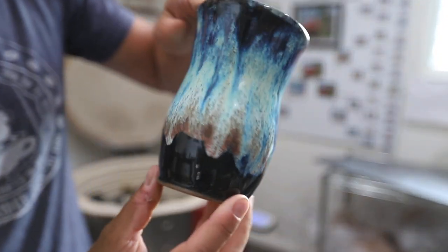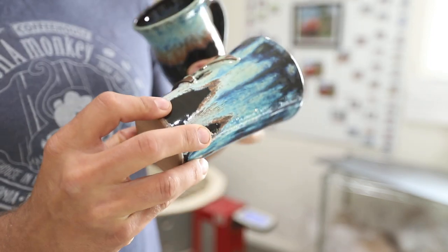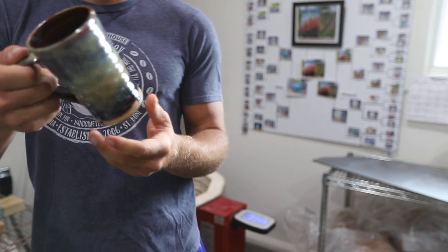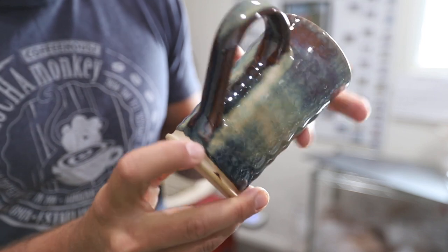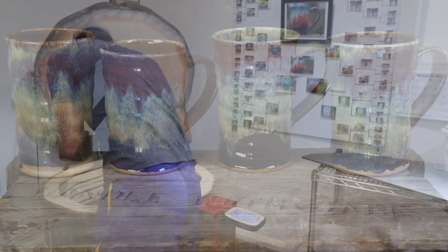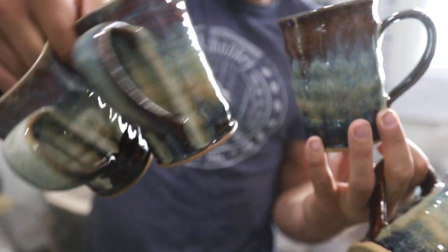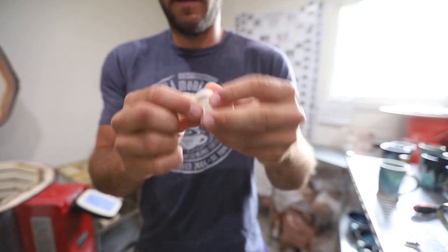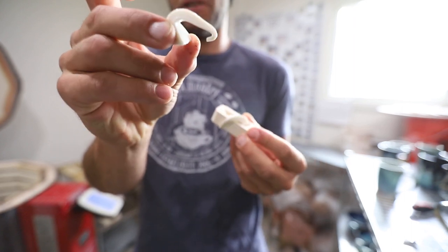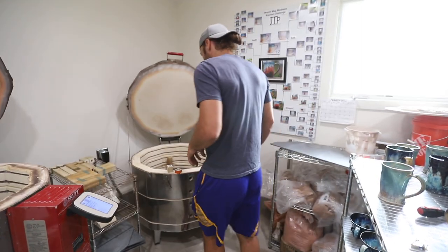There's a Northern Lights mug that dripped all the way to the bottom and off. Not sure why it's dripping over the top of the Minnesota. The glaze I haven't done in forever — Canyon Skies. If you guys have been following this channel for a while, you remember I used to do this glaze all the time and a lot of people still ask for it. So I thought, you know what, I'll do a few Canyon Skies mugs — there are four of them and those turned out really good. I've been having some issues with my one big kiln, so I figured I need to start putting witness cones in. This is the cone seven witness cone and this is cone six. Cone six melted pretty well — too much actually — so we know it was more than cone six, and the seven went pretty perfect. Good job, kiln — you did your job.